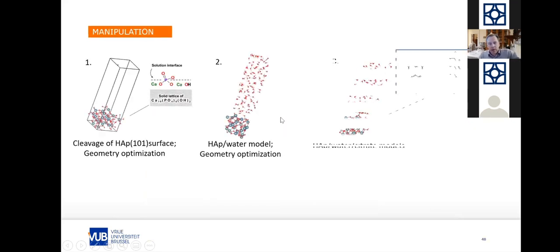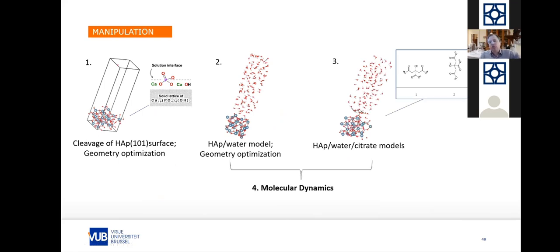Okay. Again, this is how we calculated that. We modeled, in fact, three orientations: V1, V2, and P1. Why? Because it lasted too long to wait for the orientations to equilibrate. This is the same as in the beginning of the talk, when we want to accelerate. So we know that it will be dynamic, but we need to speed up the calculation. And so we started with three intuitive structures. We are not sure, we're never sure, but as sure as we can be, not to forget any critical orientation of our complexing agent.